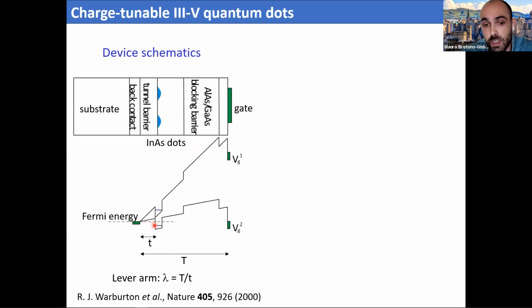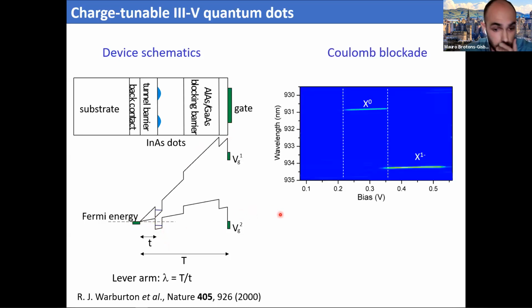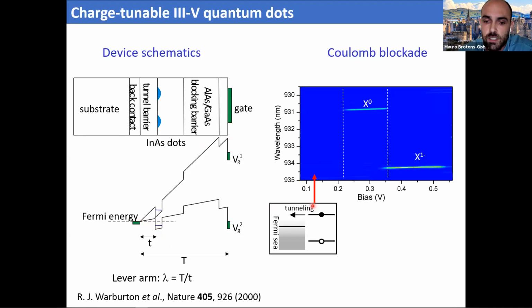So if we think from the point of view of photoluminescence experiments, basically this means the following. We can imagine the following scenarios. The first one is a scenario more or less like this, in which we have a neutral exciton in our quantum dot, and our Fermi level lies far below our confined energy level for the electrons. So if our tunneling time is faster than the recombination time, this basically means that we'll have no photoluminescence.